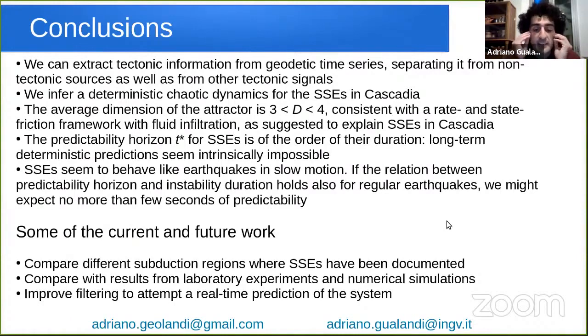Because for slow events, I find that basically this predictable horizon is of the order of days. So potentially it could be done with geodetic data. There is a problem that you have to wait for the final precise ephemerides from the GPS, which can take up to 2 weeks sometimes, or even more. And I'm applying a low-pass filter, and if you want to use a causal filter, you introduce delay in your signal. So I need to do something to solve that problem.